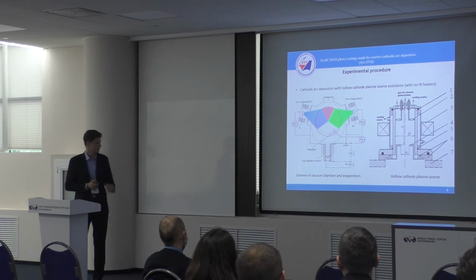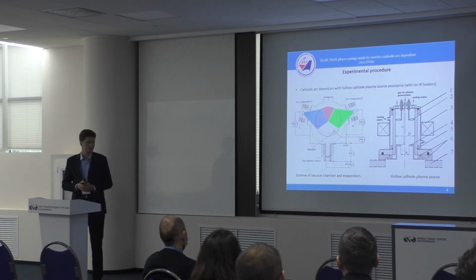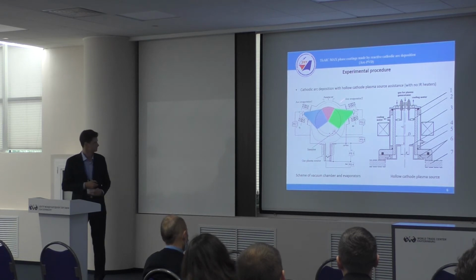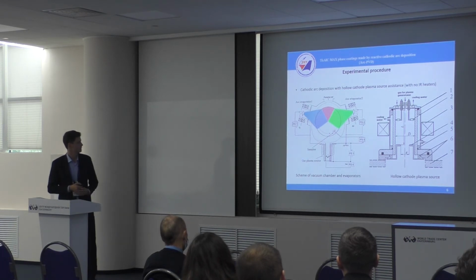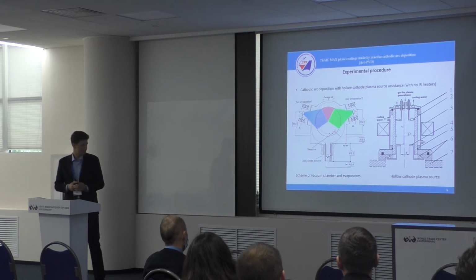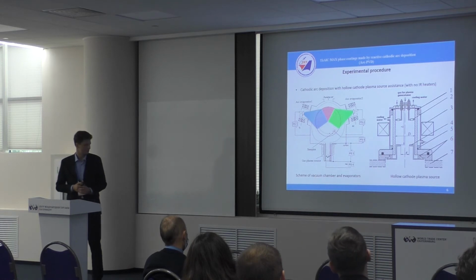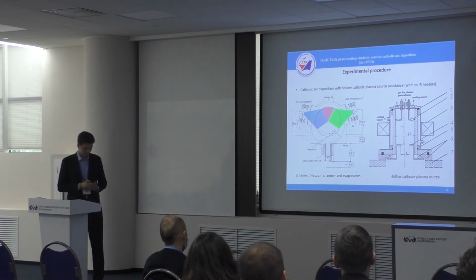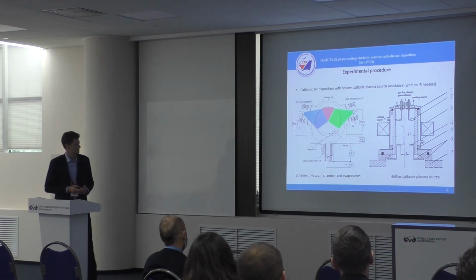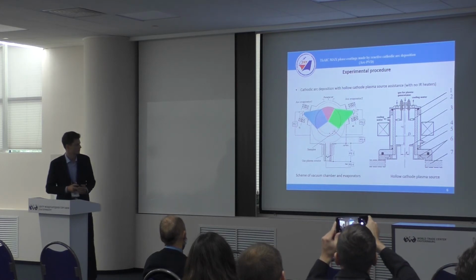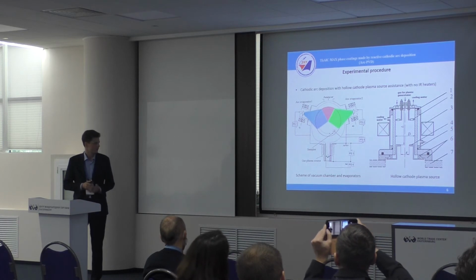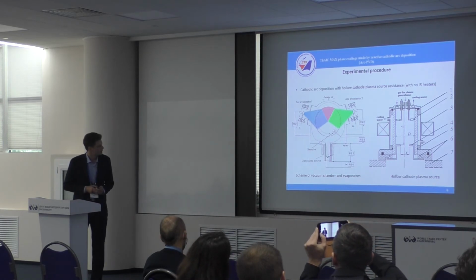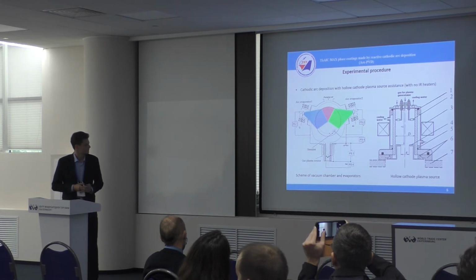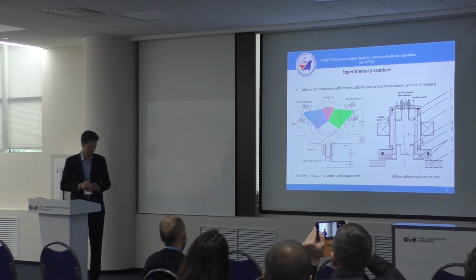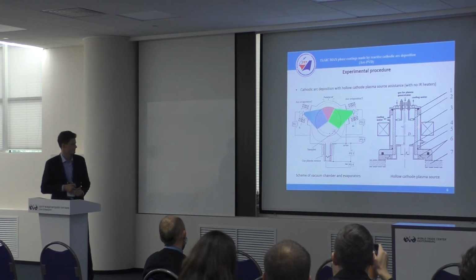Our experimental procedure. On the left picture you can see our vacuum chamber equipped with two arc evaporators, 1 and 2, titanium and aluminum respectively, and the hollow cathode plasma source which assists in the deposition process. On the right picture you can see a principal scheme of this. We obtained this from Tomsk, thanks to them. The first one is a hollow cathode. The second one is the arc igniter, the third is the magnetic coil, the fourth is the arc suppressor, the fifth and sixth are isolators, and 7 is the vacuum chamber. The plasma comes along the axis into the vacuum chamber.